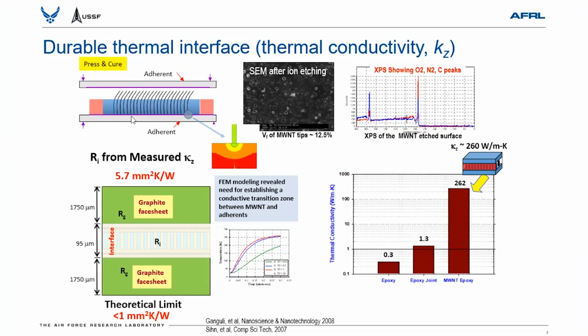So we developed a process. We used aligned carbon nanotube, then infused polymer and etched away polymer from the tips of the carbon nanotube to make a thermal contact. And that's what we came up with from our finite element calculations to create the thermal contact through thickness of the bonded joint. And in this process, after etching polymer, then we decorated tips of carbon nanotube with metallization, and it's called ion etching, and that is documented here. And then we cured the bonded joint. And with doing so, we created a thermally conductive bonded joint that is applicable to satellite application, satellite design and structural component.